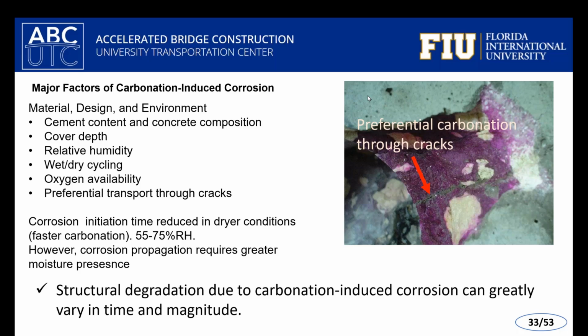Just as you can imagine, if you have goldfish in a fish bowl, sometimes we have to bubble the water to promote more oxygen being inside that water. So oxygen has to be present in the water and electrolyte in the concrete. If you have a wet environment, there may not be high level oxygen. So even though thermodynamically you may have corrosion active, your corrosion rate may not be significant enough to really affect the overall longevity of the structure if you don't promote that reduction reaction.